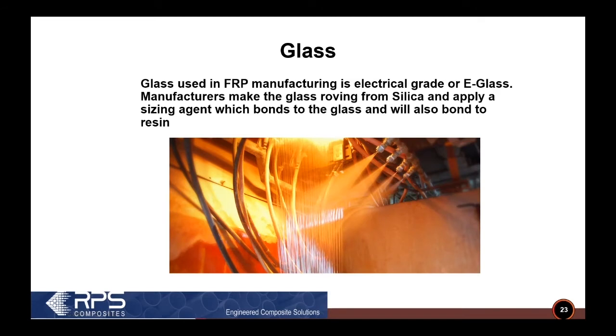On the glass side, we actually use glass to reinforce fiberglass because it's the most inexpensive, relatively speaking, of the reinforcements. When you talk about carbon fiber or Kevlar or armored reinforcements, glass is made from silica, which makes it much more inexpensive. And basically what the glass manufacturers like Owens Corning do is take silica, heat it up to a molten state, put it down through fine dies, and then they apply a sizing agent to the glass.